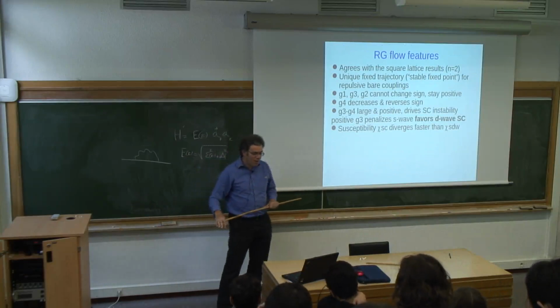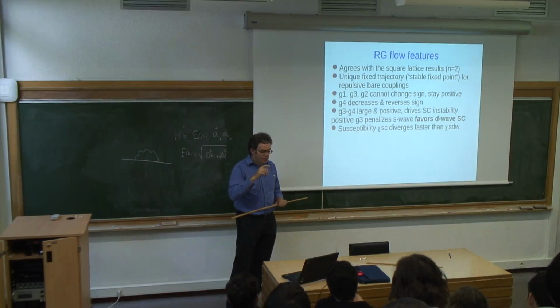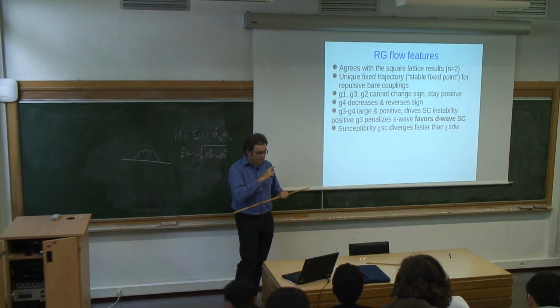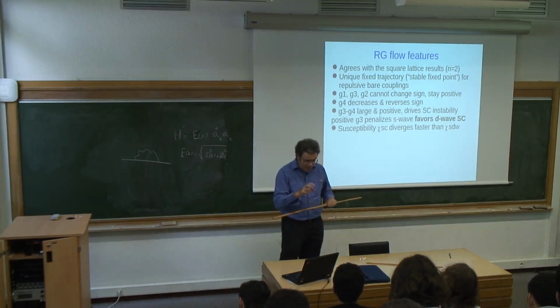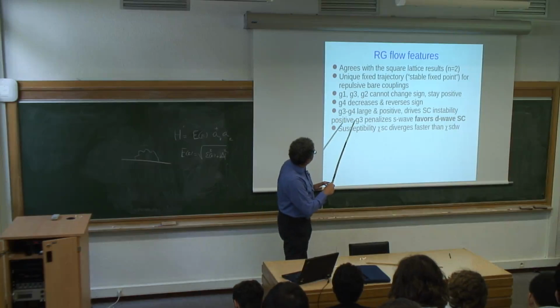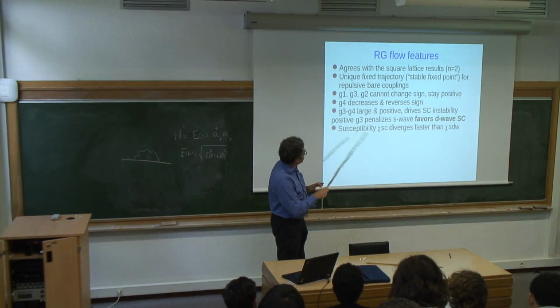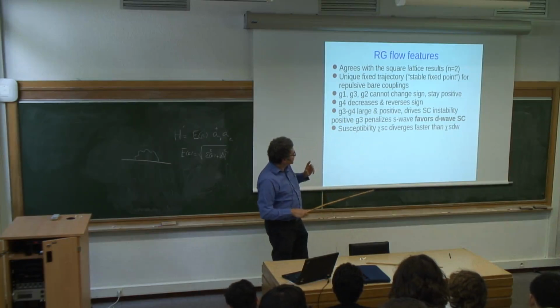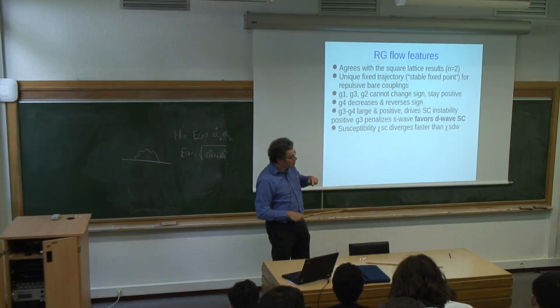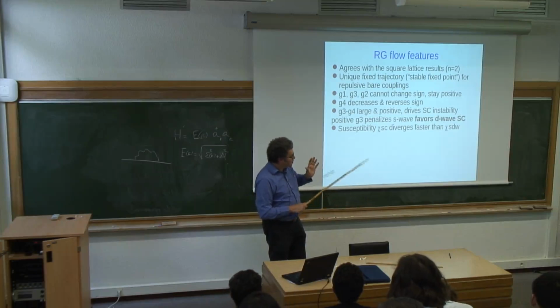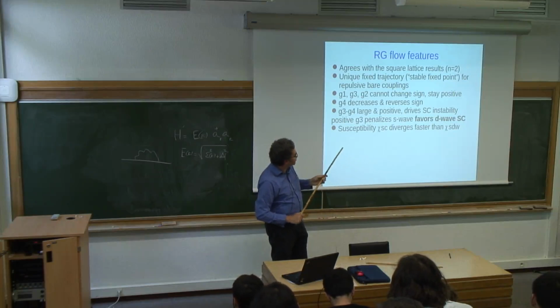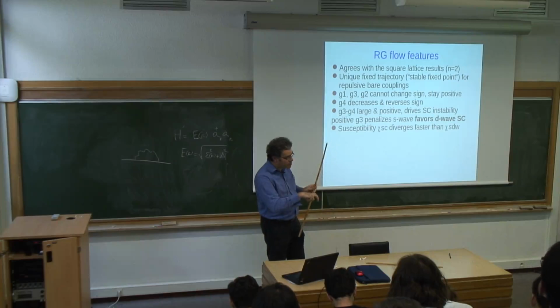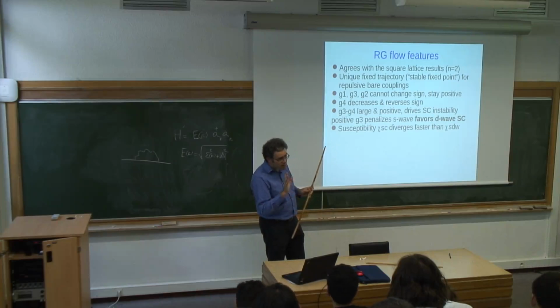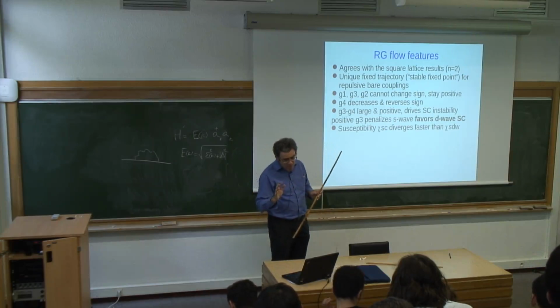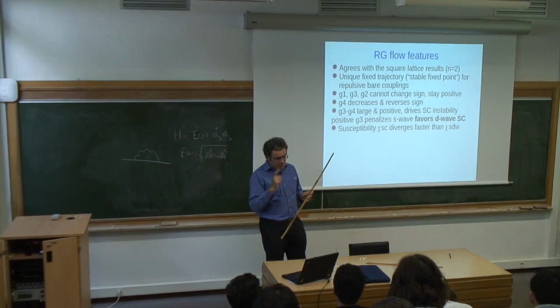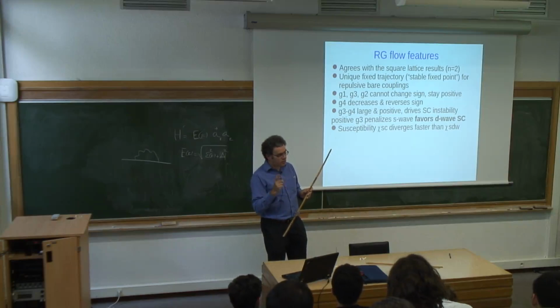don't force me to give this talk. If you study the competition between different orders, then you find that in the square lattice, the different couplings that appear can drive, they all diverge, and they can drive the system into a superconducting state and also into a spin density wave state. And in the square lattice, it's basically a messy problem which is still unsolved. And then in this case, because there are 3 saddle points instead of 2, and this is the only difference, the RG equations look very similar, but they pick a unique state. The RG flow picks a unique state.